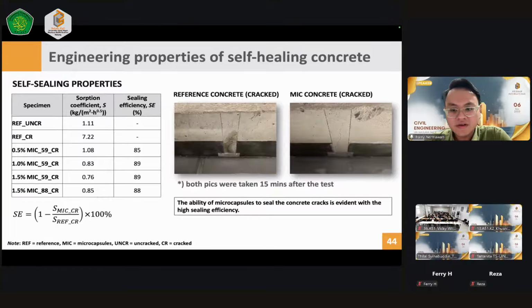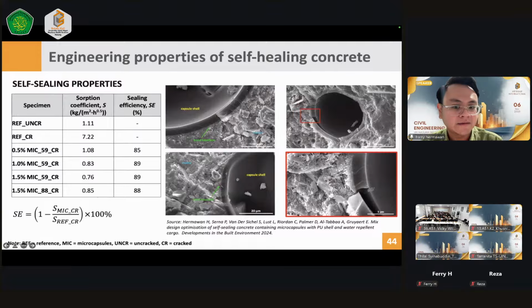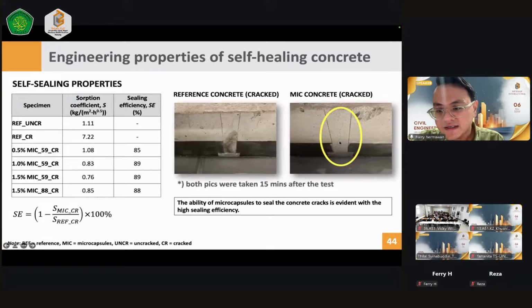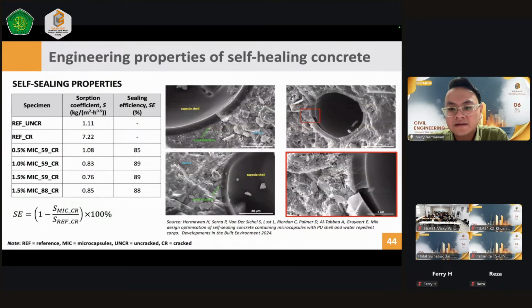Why does it happen? Because if you look at the microstructure, the capsules broke inside the matrix due to the cracking. Because of the breakage of the capsules, the sealing agent inside is released into the matrix and seals the crack. That is why you see very limited water penetration into the crack. And if we calculate the sealing efficiency based on this test, we found that the sealing efficiency reached above 85%, which is very good. Okay, so this is some proof of how we can integrate the microcapsules in order to improve the durability aspect of our concrete materials.